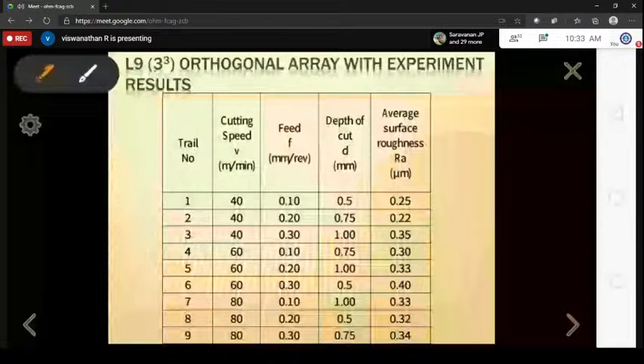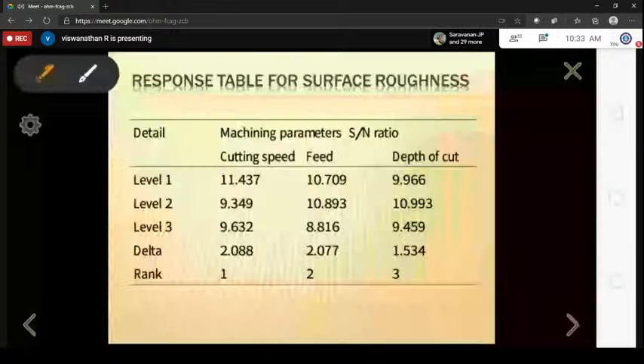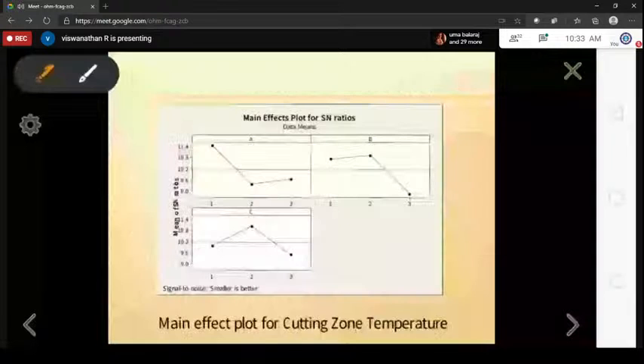After conducting the experiment, we analyzed the roughness value using the Taguchi method. We found the response table using the SN ratio. Based on the SN ratio table, for cutting speed, level 1 has the better value. For feed, level 2 has the maximum value, and for depth of cut, level 2 has the maximum value. The maximum SN ratio value gives the optimum turning parameters for machining the magnesium alloy to get the minimum surface roughness value. The picture shows the main effect plot for the SN ratio, which is plotted based on the response table.